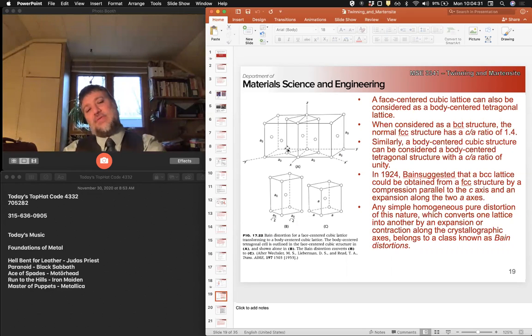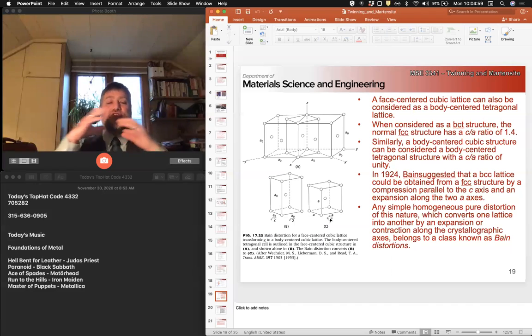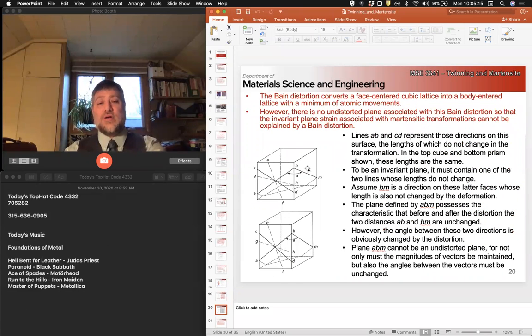And so Bain said, well, this is obviously way too distorted. This is much too tetragonal. But what I could do is squish it down a little bit and make it more square, right? And this is what he called the Bain strain. This is what is now called the Bain strain, okay? And so by expanding or contracting these crystallographic axes, we get what is known as the Bain distortions. However, this theory, as we went on, we realized is not true, okay?